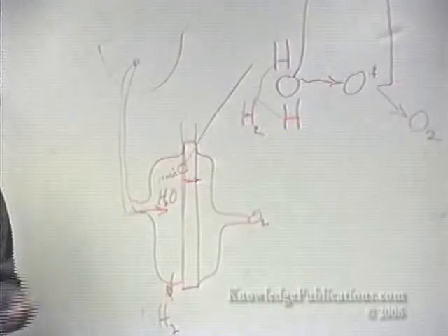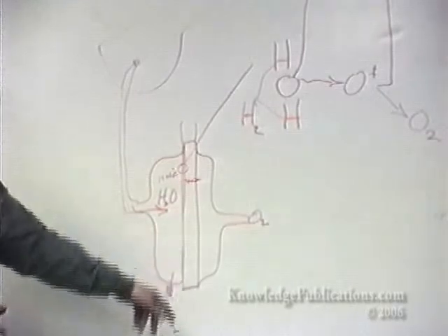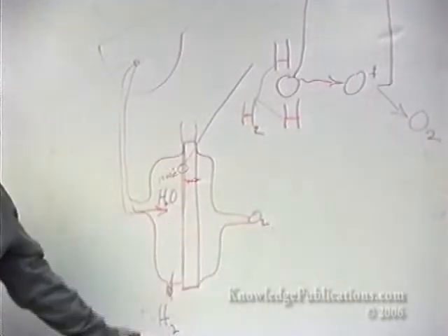On the other side, we give back the electron and produce oxygen. We run a forced delivery of electrons to where we want the oxygen to take it after stripping it to release the hydrogen. The voltage doesn't turn out to be 1.4 volts to do this. The voltage goes down as the temperature goes up. So we can get below the voltage of the fuel cell, that is the room temperature fuel cell.